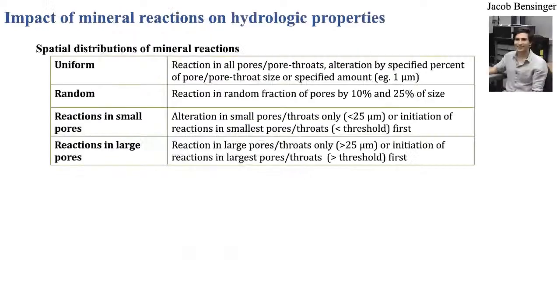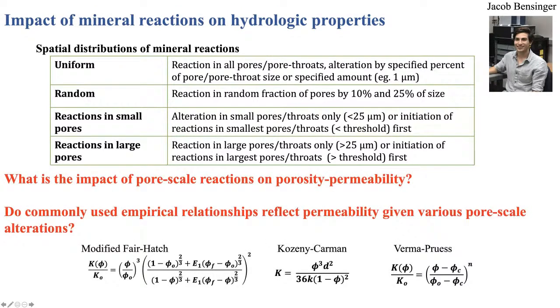And so we've done this considering a variety of different spatial distributions of reactions in the network. We've looked at uniform reactions on all surfaces, randomly distributed reactions, which correspond to only a fraction of minerals being reactive, and then reactions that are size dependent, occurring only in small or large pores, or initiating in small and large pores. And then try to understand how porosity and permeability evolve, and then whether or not these empirical relationships are able to reflect those alterations. This work was done by my undergrad researcher, Jacob Bensinger.